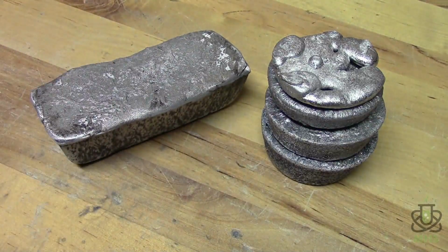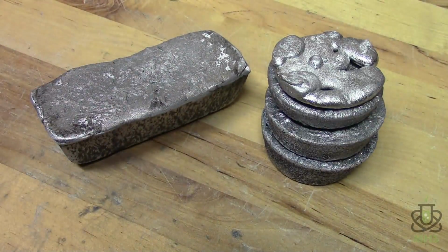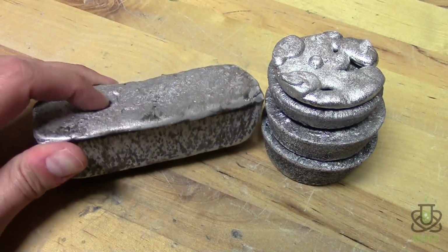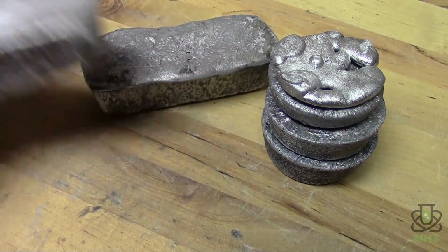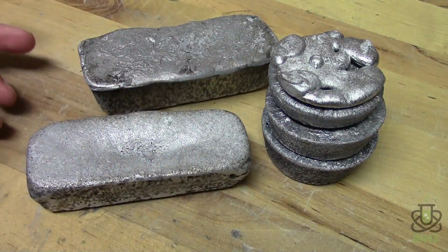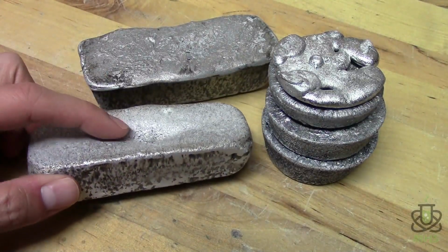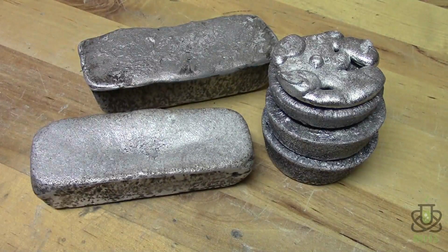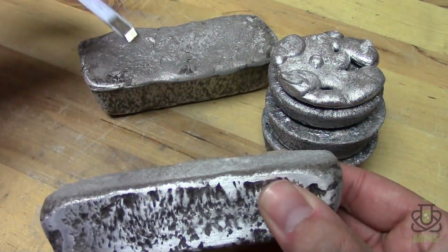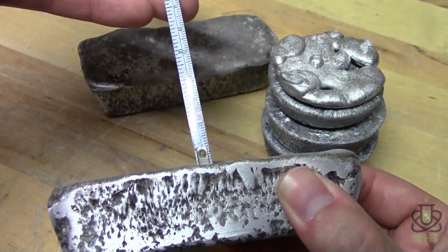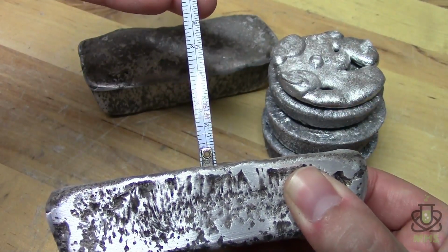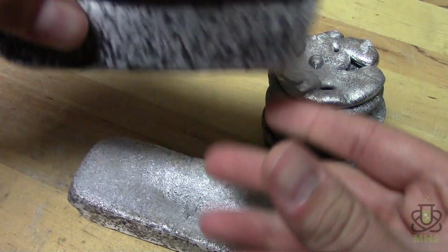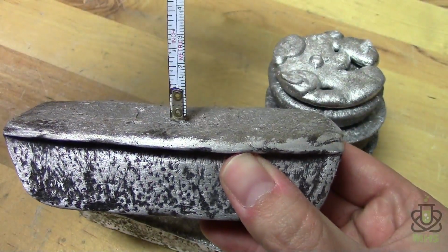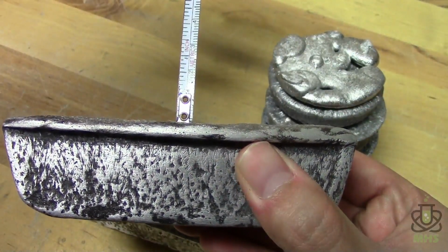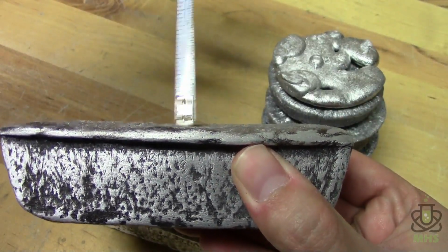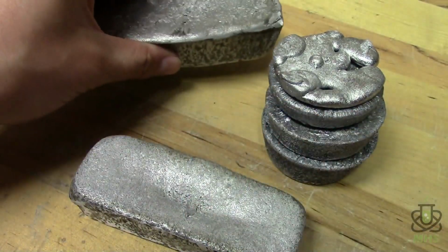But the reason that this particular alloy is really good for casting is because of shrinkage. This alloy doesn't shrink nearly as much as pure aluminum. So for comparison, here is a bar of soda can aluminum, which is not casting grade, and you can see this big dimple in the middle, how much it's actually shrunk. So let me try to give you a little bit better view of that. There's a measuring tape I'll put down in there, and so you see how far down that goes. And if we compare that to what this bar has, practically no shrink at all. It's almost totally flat up here, which is great.